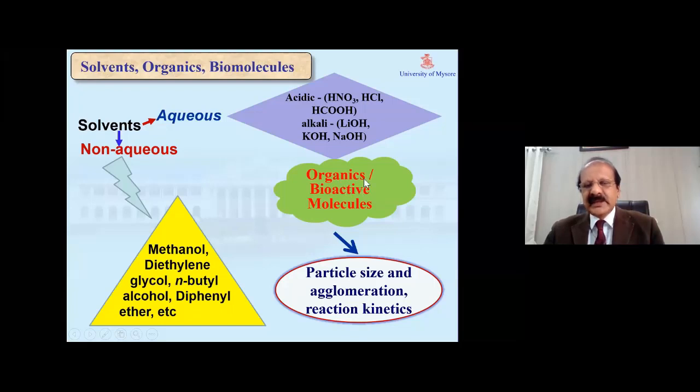And nowadays organics are added into any of these, some organic molecules, and even biomolecules are added. When I say organic, it is nothing but the fatty organic acids. That is the modifier or the surfactant. The same thing with bioactive molecules, maybe the phytochemicals or plant extracts. So they also act as surfactants. They can be used for controlling the particle size, to prevent agglomeration, and to enhance the reaction kinetics. In fact, what materials we could prepare in 10 days or 8 days, we could prepare in just a few hours or even a few minutes.